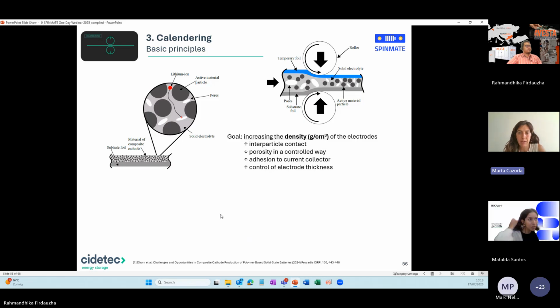So then while we have the coating, there's a very important step, that is the calendaring. First of all, when we have a coated electrode, here we see in this magnified picture, we have lithium ions that transport through the cathode. So in our active material particles, we know that these are lithium ion conductive. But then when we reach some pores, these pores are not lithium ion conductive, because it is the solid electrolyte, or catholyte as we call it as well, that allows the lithium ion transport. So we want to reduce this porosity to assure that we have a correct lithium ion transport within the electrode matrix.